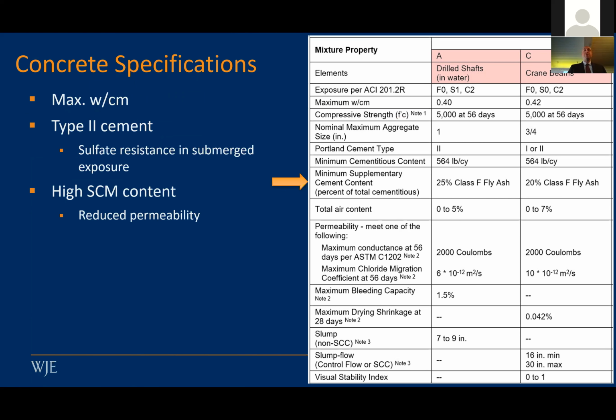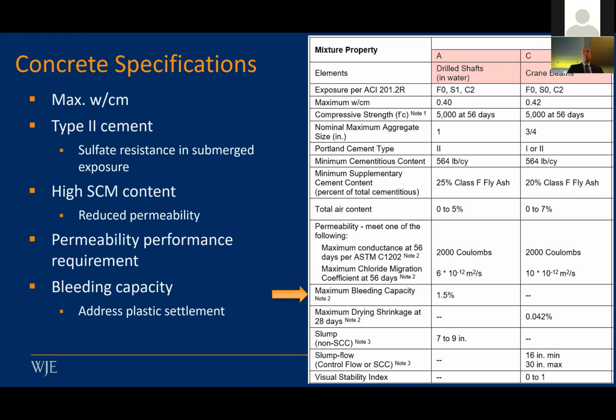Different supplemental cementitious material contents. We needed reduced permeability in our drilled shafts because of the exposure to the chlorides, and then we wanted to see that impact from test results. We also had some bleeding restrictions because of previous problems at some of the other locations, as well as a max drying shrinkage.